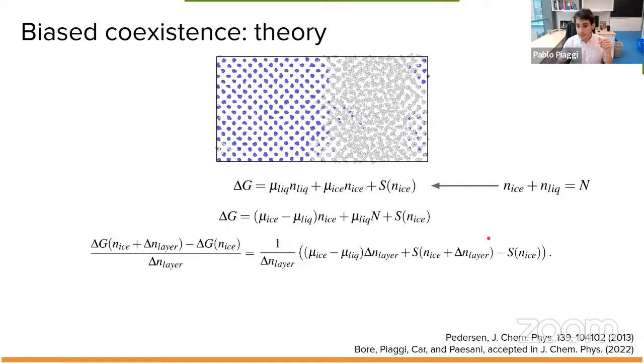And here we have to make an important assumption, that is that if this surface term is periodic over one layer, which makes sense, I mean, the formation of a layer takes the system to a configuration that from the point of view of the interface is indistinguishable from the previous one, then we can cancel out these two terms. And we end up with a very simple formula and idea, that is that the slope of the free energy as a function of the number of ice-like molecules will give us the difference in chemical potential between the two phases that we're studying. And that's the idea of this method.